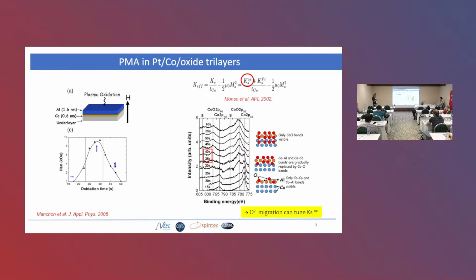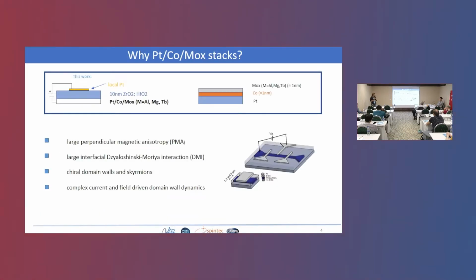So what we had, as I said in the previous works, people used this gadolinium oxide that is an ion conductor. We had a slightly different approach. So we used platinum cobalt oxide tri-layers in which we change the oxide, the metal. We actually studied aluminum, magnesium, and terbium. We pattern it. So why do we use this multi-layer?